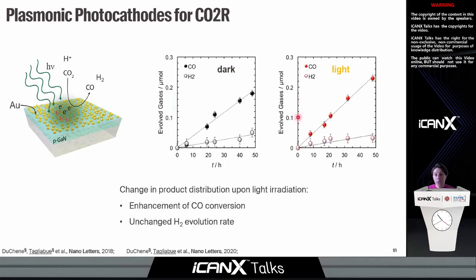What about the products then? Well, we measured the generation of carbon monoxide and hydrogen in dark. We have a certain evolution with time. And then we repeated the same measurement under illumination. And although the quantities are pretty low, we could see a 20% increase selectively on the generation of carbon monoxide.